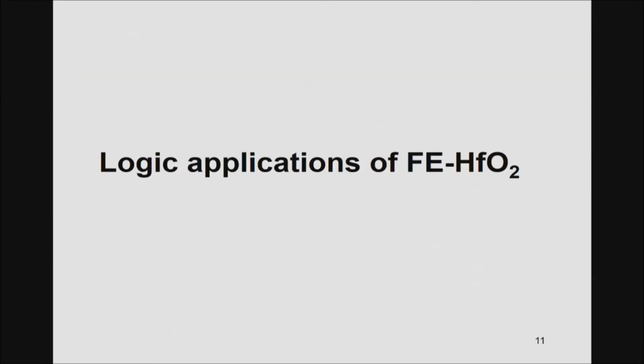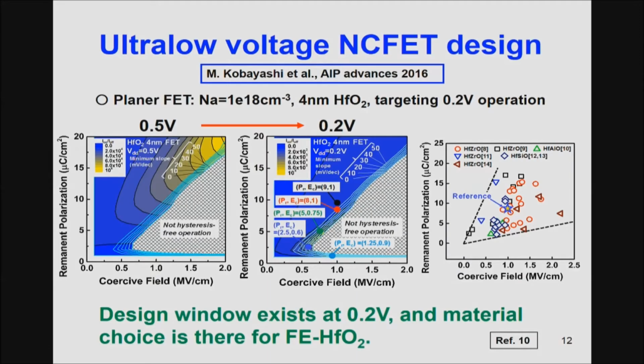Okay, based on this background, I'm going through some activity on a negative capacitance FET using ferroelectric hafnium oxide. My first interest was how low a voltage the NCFET can operate at. So I studied modeling and simulation for the low voltage NCFET. The device structure is just a planar FET targeting 0.2 volt operation. It's maybe ridiculously too low, but I targeted 0.2 volt. This graph shows the I-on/I-off ratio contour plot as a function of material parameters, remnant polarization PR and the coercive field EC. Luckily, there is a process window even at 0.2 volt.